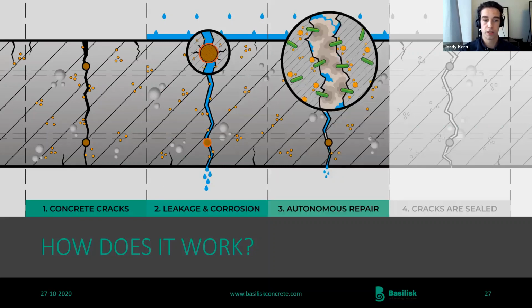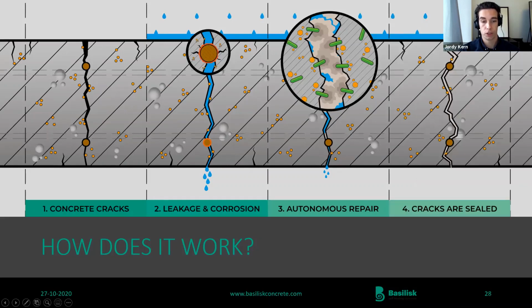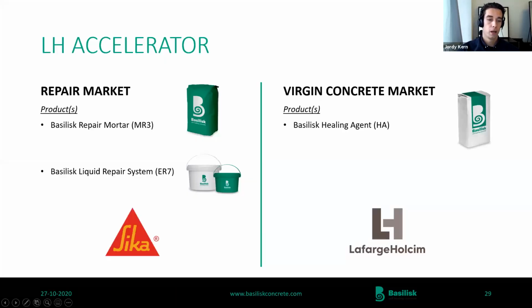Well, that's where our self-healing technology comes into play. By incorporating bacteria and nutrients into the concrete, we introduce an autonomous repair property. When in contact with water, the bacteria become active and will convert available nutrients into calcium carbonate, also known as limestone. That limestone will precipitate on the crack wall and will gradually block and seal the crack. This will prevent further leakage and will provide protection to the steel reinforcement. Our technology can be implemented as a repair system for existing structures or as an additive for virgin concrete applications.